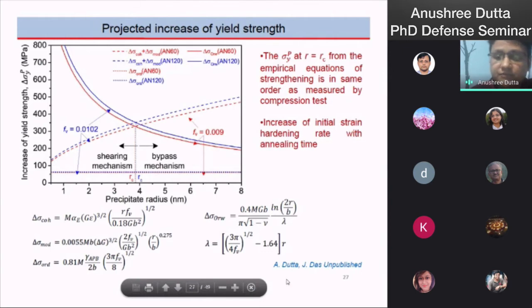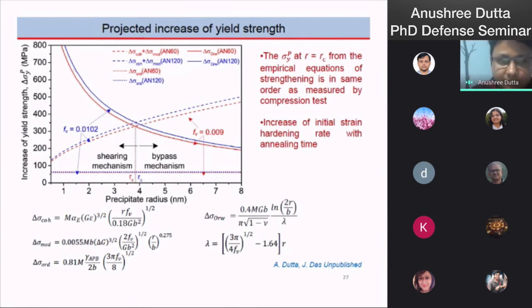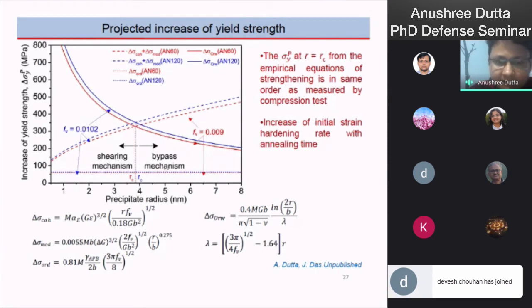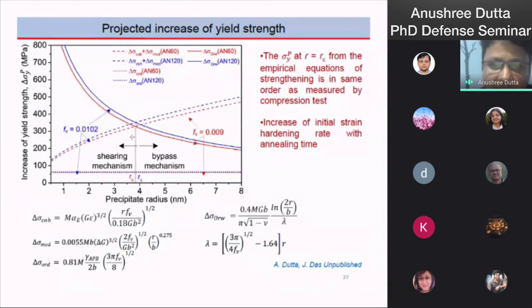The contribution from Orowan is also estimated, and we can find these two curves, this one for shearing and this one for the bypass mechanism. These two curves cut at this point, which is the critical radius. At lower than the critical radius, the shearing mechanism is dominant, and at higher than the critical radius, the bypass mechanism is the dominating mechanism of strengthening.